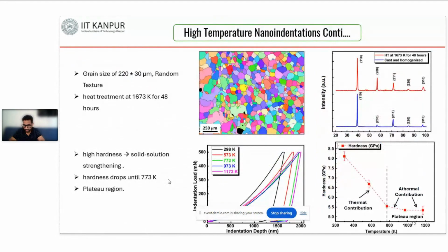So with this NanoTest Extreme setup, we are able to measure high temperature nanoindentation. But before the nanoindentation, I did a rigorous microstructure characterization to find out the grain size and the texture information. In the EBSD image we got a random texture, and at room temperature we have a BCC structure. To check the phase stability of this BCC structure at high temperature, we did a heat treatment at almost 1673 Kelvin for 48 hours, and we found that even at such a high temperature and for a long time we got a single phase structure. So we confirmed that this is a single phase structure, even at high temperature.